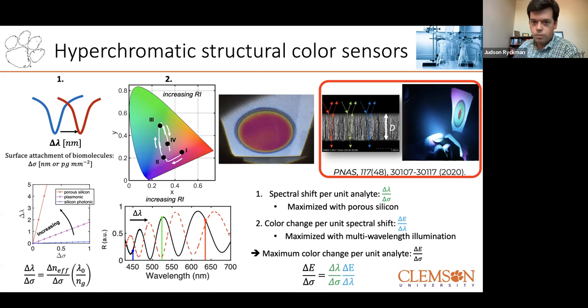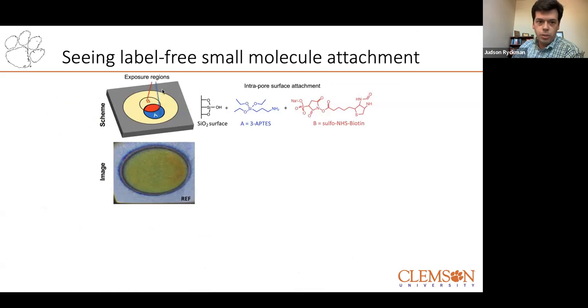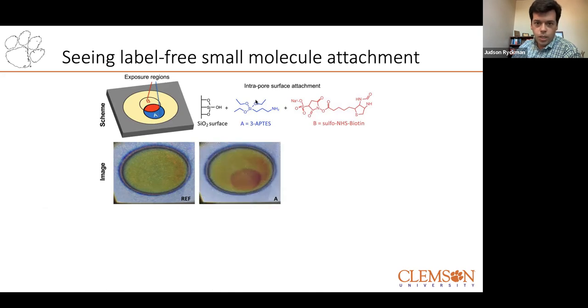I'll show just one example where we take a porous silicon chip here, and we're going to functionalize the surface, and we'll be able to see it by the naked eye, despite the fact that these molecules are, in this case, about a 0.8 nanometer, roughly a monolayer, versus about a 1.5 nanometer to 2 nanometer molecule. So we're going to do this Venn diagram type experiment. So we'll silanize the surface to give a nice amine termination, and then we'll come in with this sulfo NHS to bind to the available amine termination.